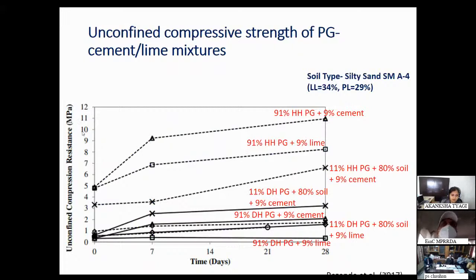So it can go up to, say, 10 MPa, and the dihydrate is up to 1 or 2 MPa. But again, it depends on the type of application you want to use this kind of material. If for your use 1 MPa is okay, then it's fine. I mean, you don't have to go for very high strengths. But for more strength, it may be noted that hemihydrate phosphogypsum is known to have higher strength than the dihydrate. And why is it so?